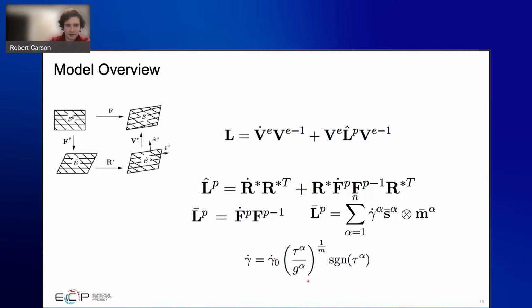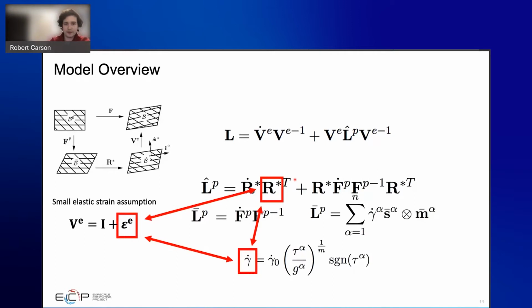I mentioned earlier that we have this small elastic strain assumption. You can replace your elastic left stretch tensor with this set of equations here, and you can simplify everything even further, so it's all represented with your elastic strain. The reason I want to bring this up is to highlight that the evolution of our elastic strains, lattice rotations, and our slip rates are all dependent on one another. Due to this fact and the fact that some of our equations are highly nonlinear, solving for the updates of our states can be quite computationally expensive, more so than your typical constitutive equation for your models.